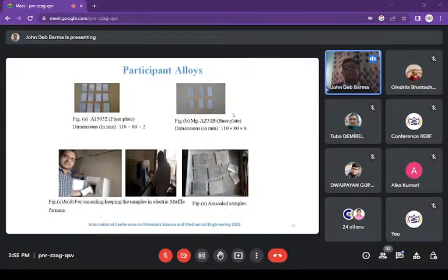Now, these are the participant alloys, and here also the dimensions which have been considered are shown. As you can see in this slide, the dimensions of the aluminum alloy are kept as 110 by 80 by 2 mm, and for the base plate it is more, so it is 110 by 80 by 6. And annealing is done so that it achieves the strength. So the electric muffle furnace was used, and figure E shows the annealed samples.